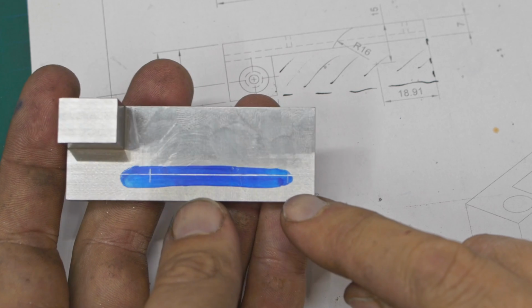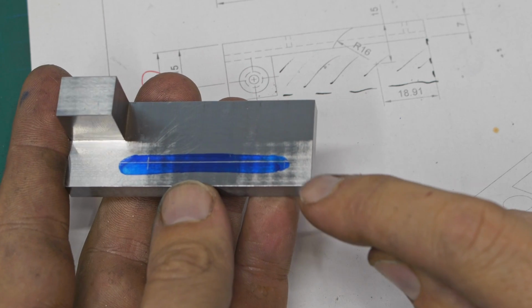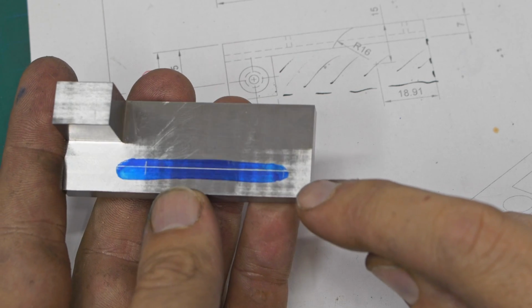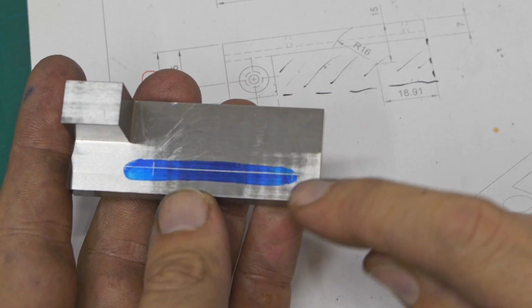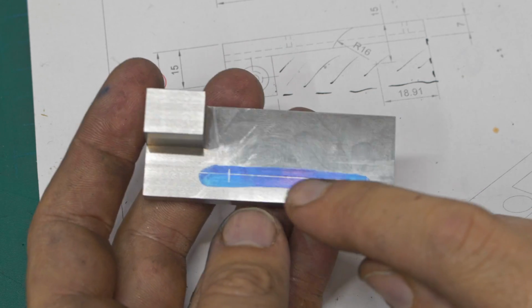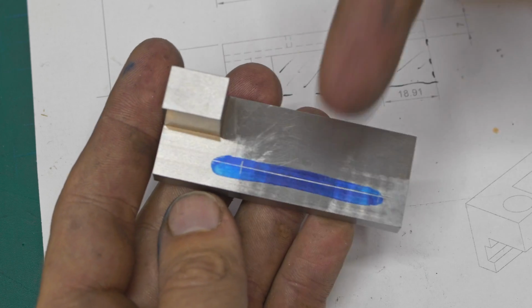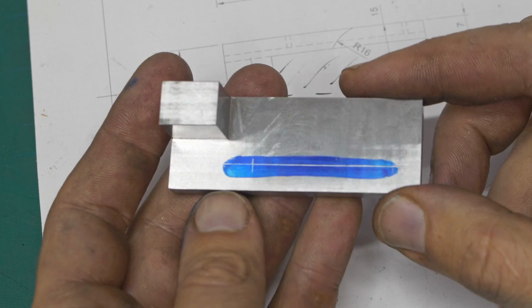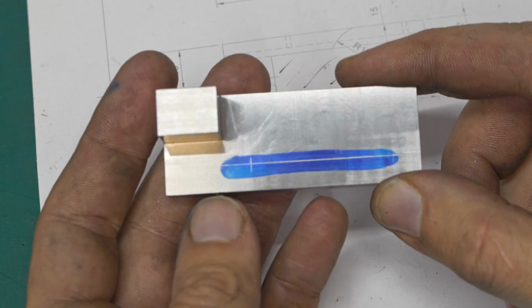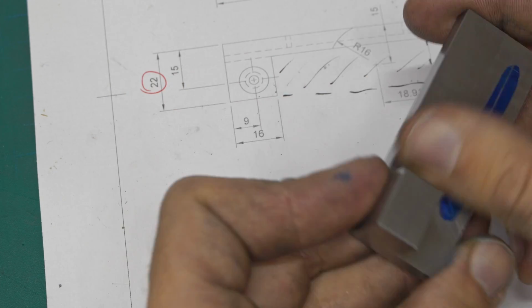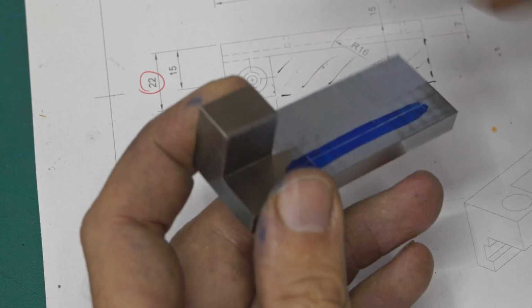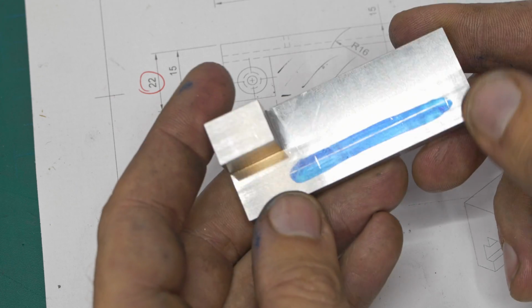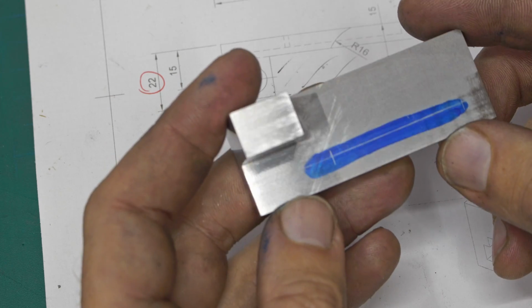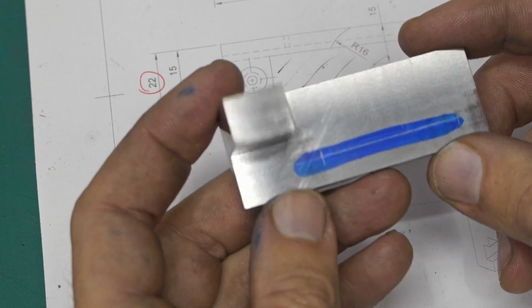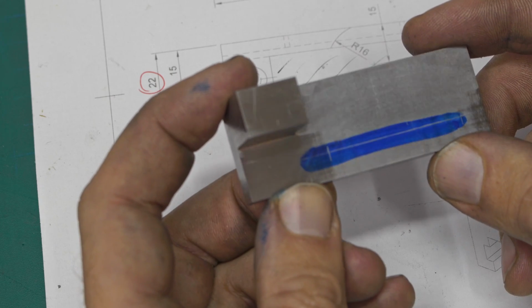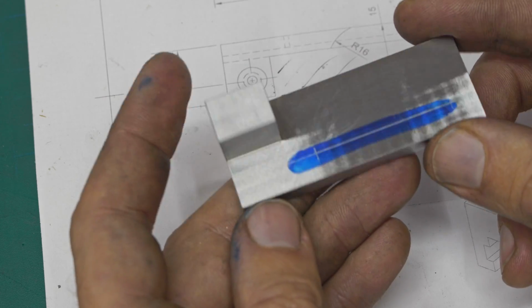As you can see, the blend line, the crosshatch of the grinding wheel is fading out here. It's making contact, and it's making contact here, and it's a little bit deeper here, the 90-degree way. And honestly, it doesn't matter for what this is. But once I hit it with some Scotch-Brite and clean everything up, this will give a very even overall finish, which will very nicely fare over time, especially once it's plasma nitrided.